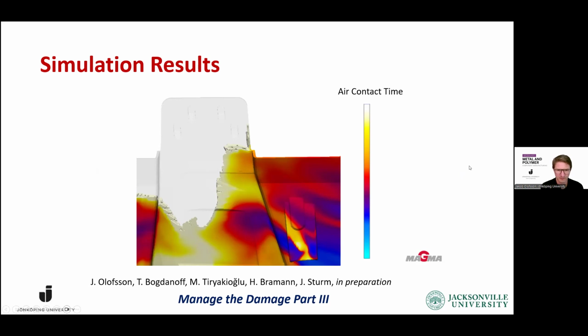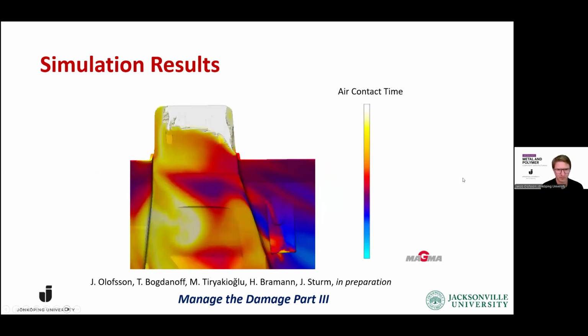As you can see, this is at the end of filling, where we see how the melt fronts are approaching this location. And it's actually 3 different melt fronts coming from different regions. You can see one coming from above that has been in contact with air for a long time. And if you proceed to the next image, you see that these 3 fronts have smashed together and formed a turbulent area, where the oxide films that have been generated during this long air contact time are being swirled into the melt here.